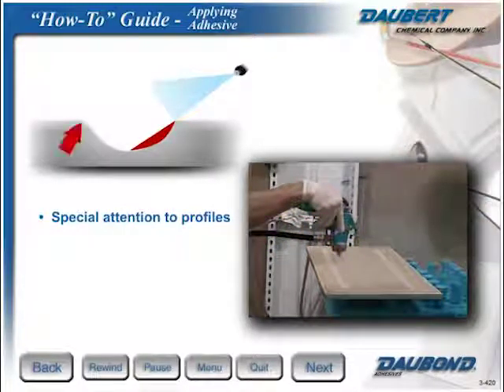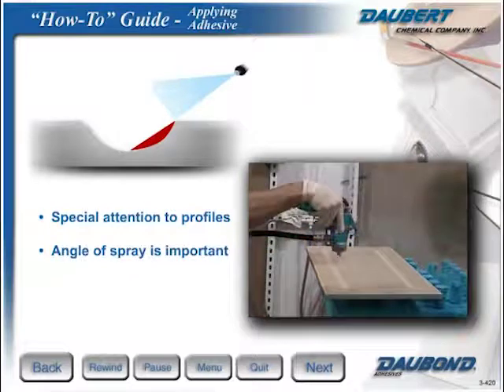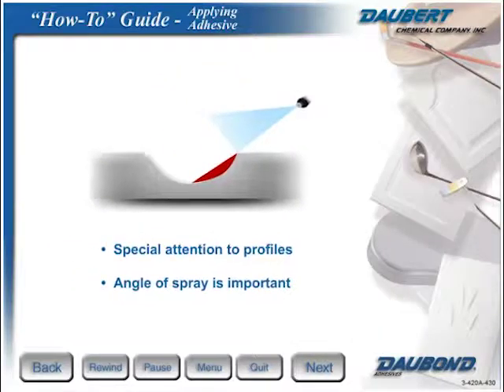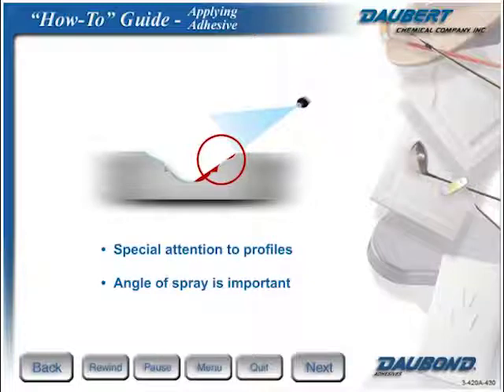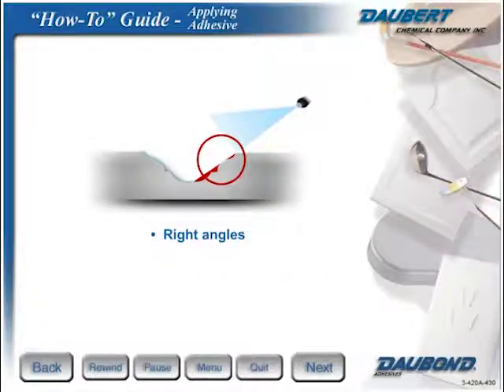For example, a simple profile like this won't have adhesive coverage in the red area because of the spray angle shown. Another example. Too little adhesive in the red area. Profiles like this often have too much adhesive on one side and not enough on the other. Always spray at right angles or perpendicular to the surface.